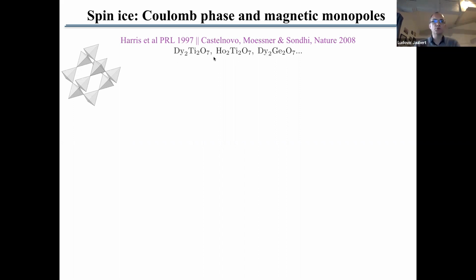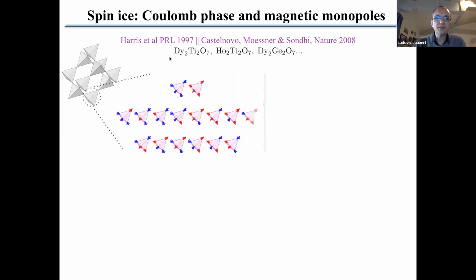So what is the model of spin-ice? Spin-ice lives on the pyrochlore lattice, which is made of corner-sharing tetrahedra like this, with Ising spins at the corners of each tetrahedron. Because they're Ising, they can take two different positions, pointing in or pointing out. With 4 corner spins, that means 2 to the 4 equals 16 possible configurations. These are the 16 possible states, with the ground state of spin ice being the configurations with 2 in and 2 out.